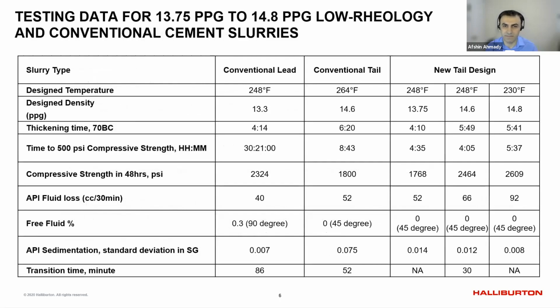Here I listed the conventional lead-tail design. That was the original design. And at the first step, we changed the tail, which had higher viscosity. We changed the tail to have a different density. At the first step, it reduced the density from 14.6 to 13.75. Sorry, it's just a weird density because I converted that one from SI units to imperial. But 13.75 was the equivalent density.